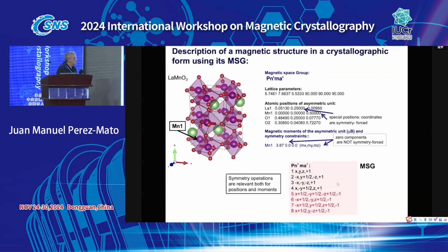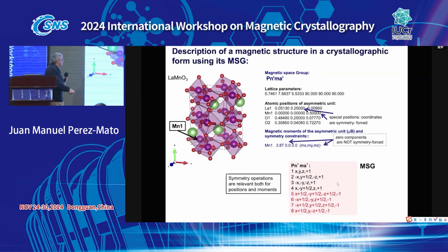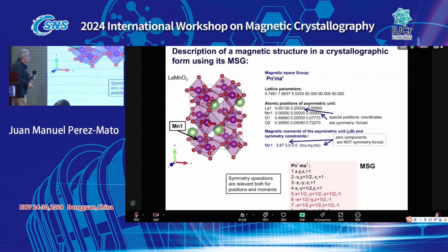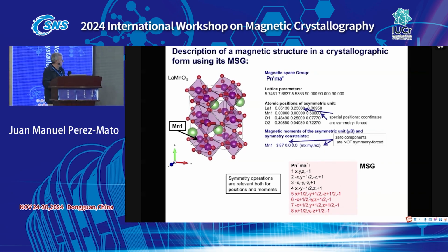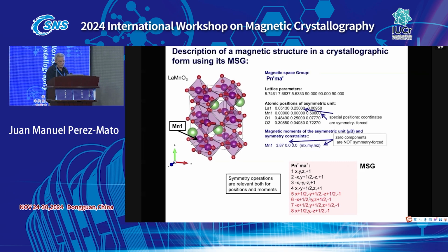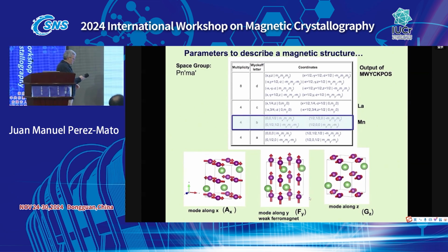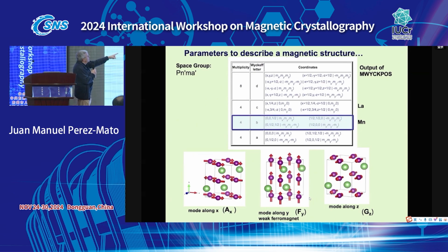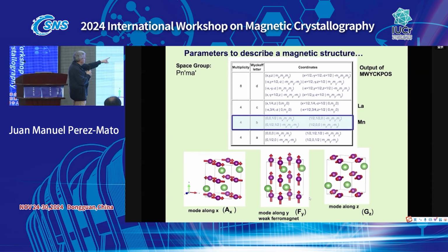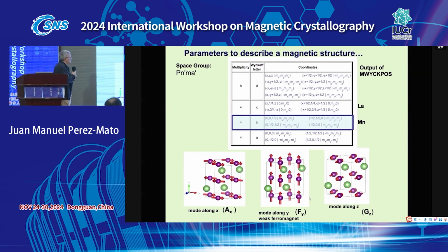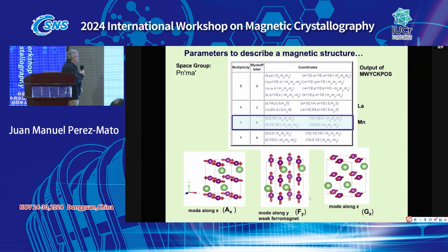the general set of these operations. So in fact, this is what is given for this particular Wyckoff orbit for manganese, that along X, Y, or Z, you have these types of arrangements which are different, and in the traditional literature, they are called A, F, or G.